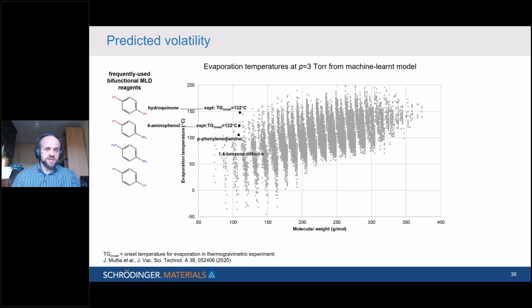Here are the 4 molecules that are commonly used. We've talked about hydroquinone. Experimentally, it has an onset of evaporation in TG, so in thermogravimetric analysis, of 132 degrees C. The predicted temperature we've come up with is 150. So other experiments give other values.